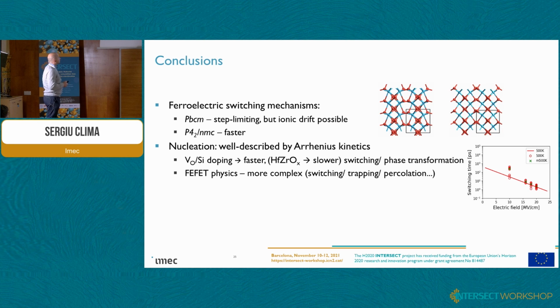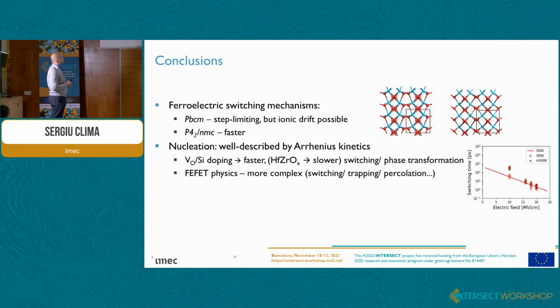The nucleation of the switching at high field and high temperatures is quite Arrhenius-like. If we have dopants or defects, they will switch faster. Strained hafnium zirconate shows slower switching, but then, question mark, what happens when you release the strain on that system?